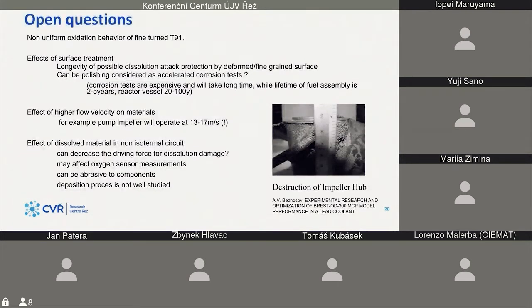So we have some open questions. Why is there not uniform behavior of T91? That's the first unknown here. Effect of surface treatment: if we found that this fine grain caused by machining or modified surface layer will be used as surface finish, how long does it last? If it's maybe just a temporary thing for 10,000 hours, we don't know. Second thing is, can we use polishing as accelerated corrosion tests? Because the corrosion tests are very long and expensive, so it will be nice to have something to speed it up.